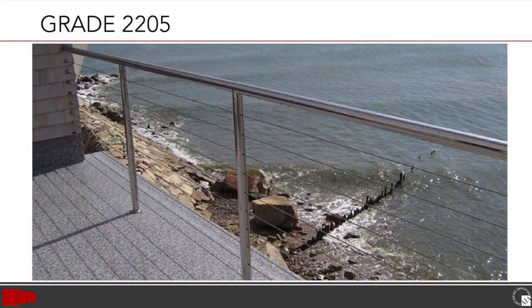Although 316 performs better than 304 when it comes to corrosion, the premium grade for high salt content regions is 2205. As we mentioned, 2205 is a duplex stainless steel grade that provides superior corrosion resistance and should be the product of choice in areas that will have an extreme exposure to salt-laden air and coastal areas. Additionally, it's worth noting that this duplex steel is generally twice as strong as austenitic and ferritic stainless steels. These higher strength alloys are capable of supporting greater loads and spanning large distances while retaining a slim and elegant form. Using duplex stainless steel can reduce the extent of routine maintenance and help retain the original appearance for an extended lifespan.